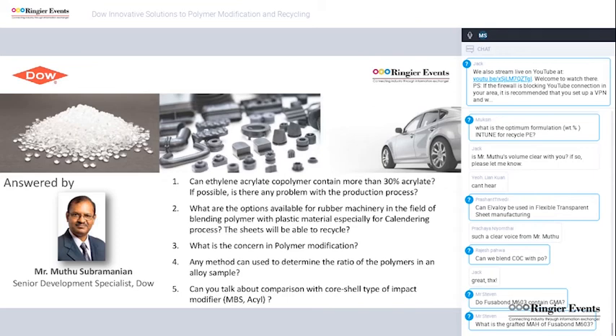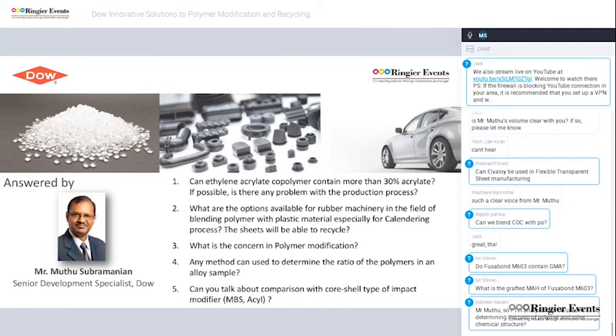This trend we also observed in the modification of ABS. So for modifying ABS, similarly, Elvaloy can improve the impact compared to the MBS and acrylic. And also, Elvaloy will be able to reduce the melt viscosity and increase the flow of ABS. And another advantage of Elvaloy is its pellet form, so easy handling, whereas MBS and acrylic are in powder form.